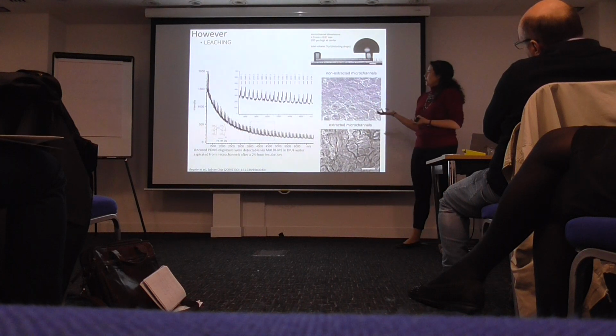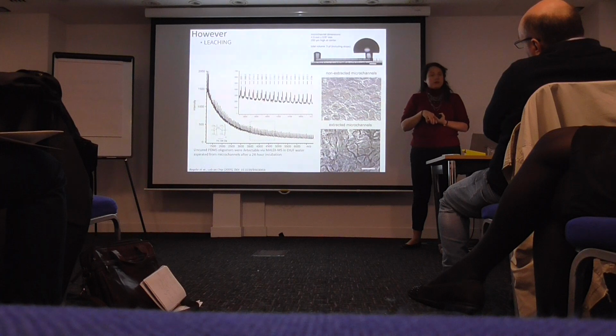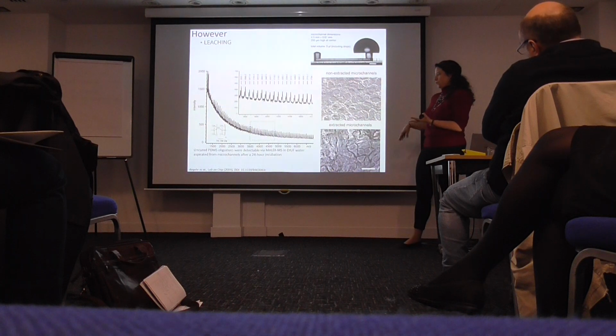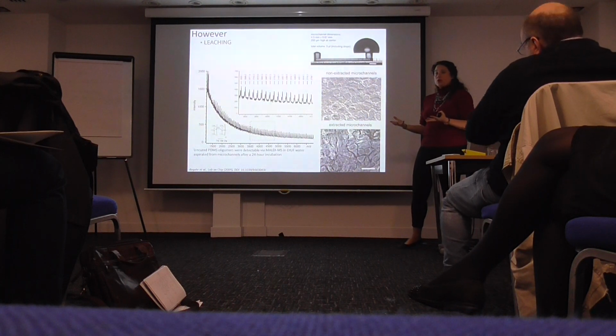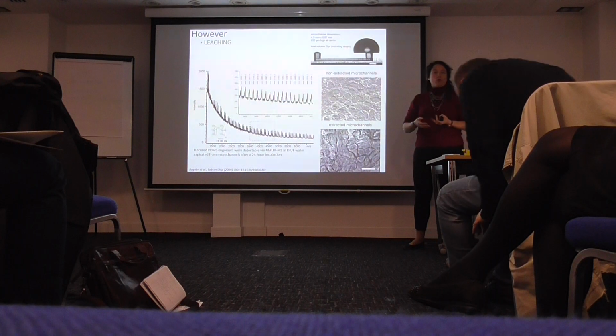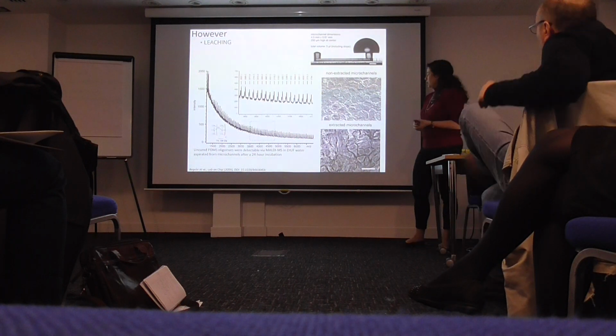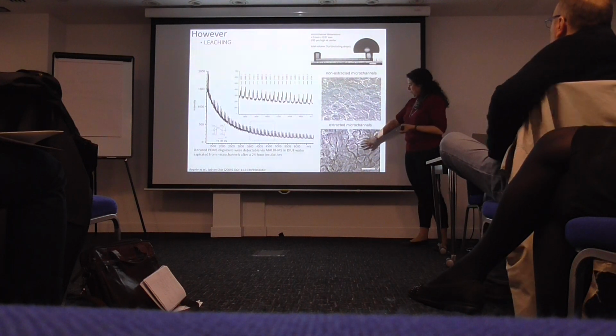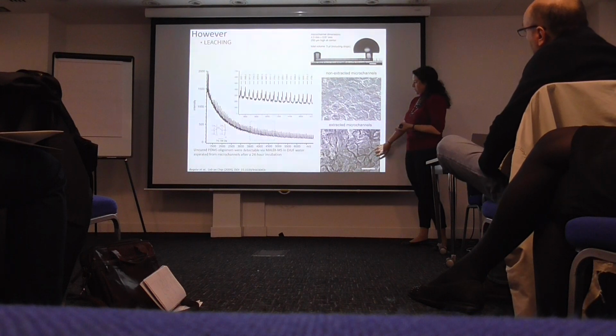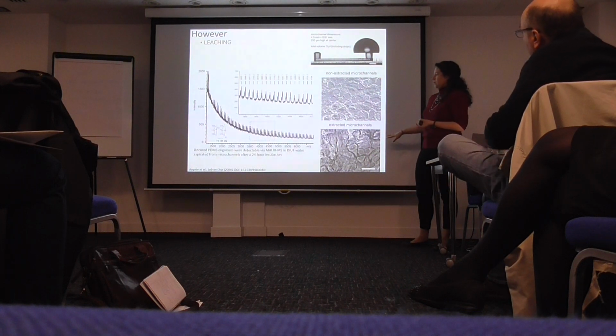Some people try to overcome that by swelling the PDMS inside of a solvent. After you've made your PDMS, you do different washes with solvent, up to 48 hours of washes, which kind of kills the whole PDMS fast. And then it doesn't get as bad once you've done some extractions. But it is something that we need to take into account.